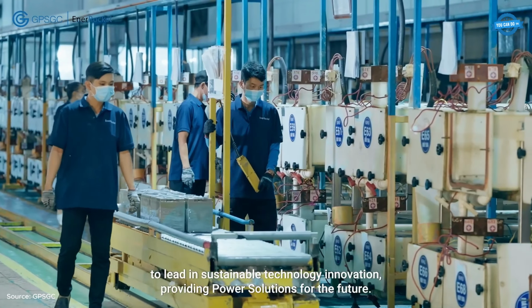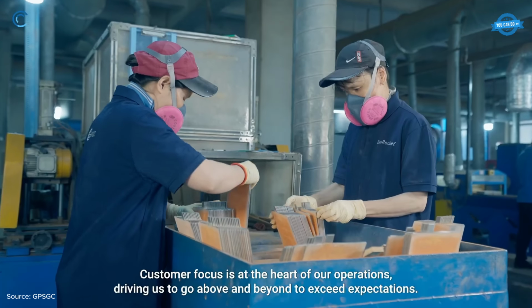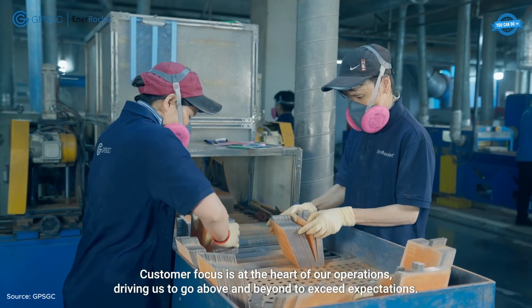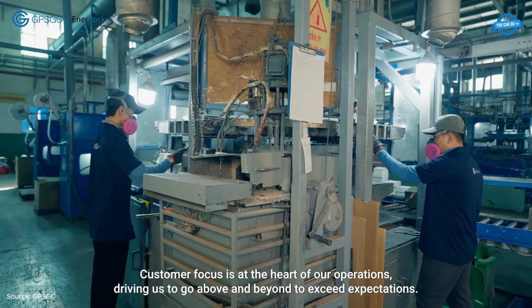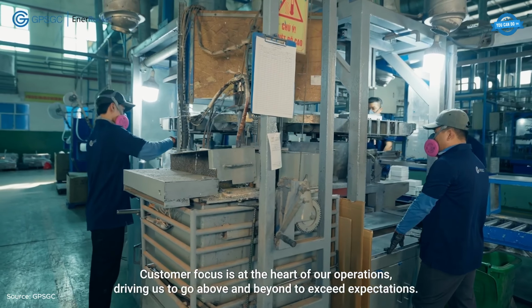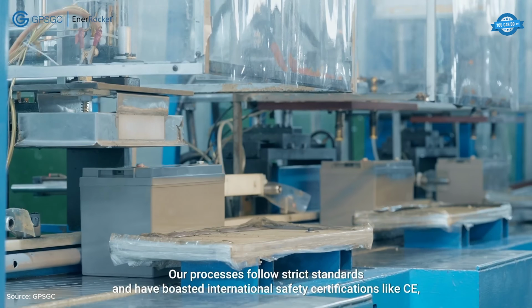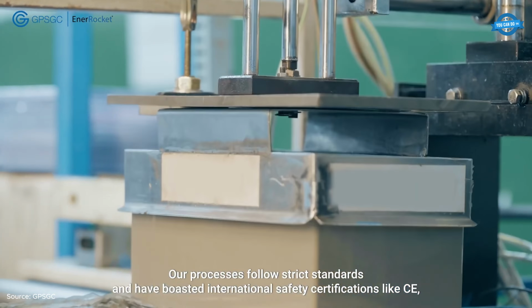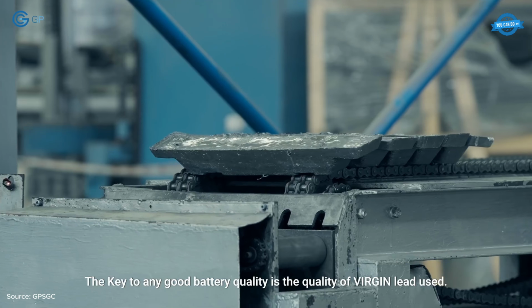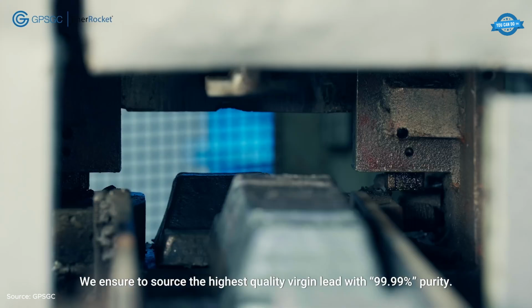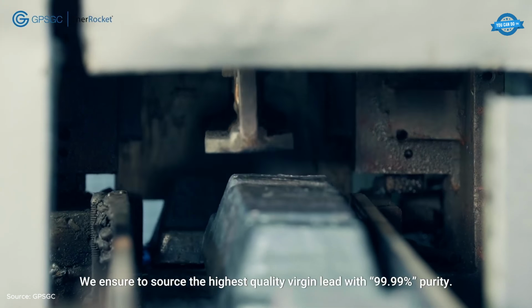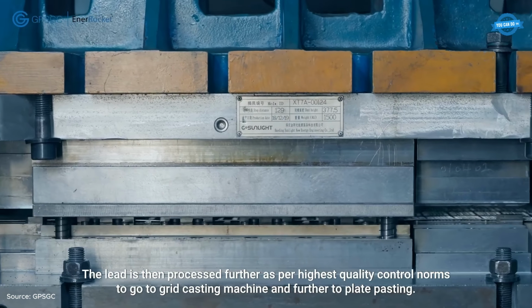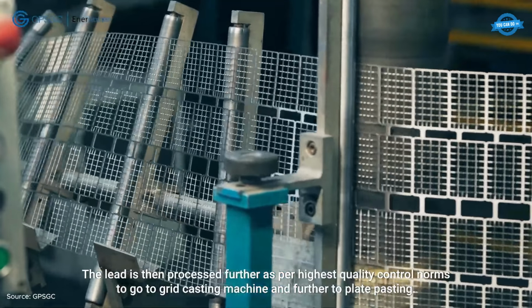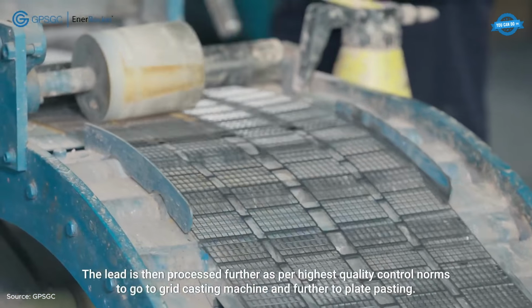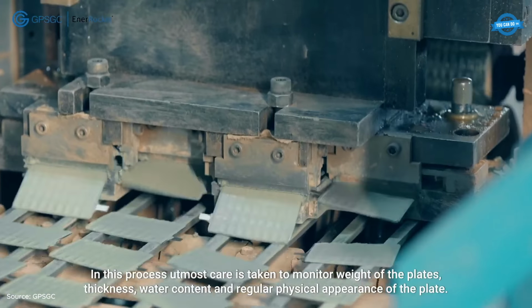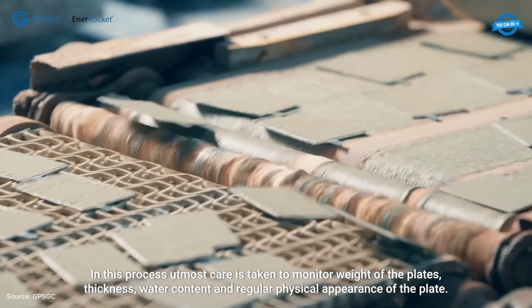EnerRocket's manufacturing complex in Ho Chi Minh City operates as a fully integrated VRLA production hub, engineered around precision plate fabrication, controlled curing, and automated assembly. The process begins with virgin lead melting and alloying, followed by grid casting on temperature-regulated continuous machines to ensure uniform thickness and metallurgical stability. These grids move to automated pasting systems, where oxide paste is applied under strict control of moisture content, density, and plate mass.